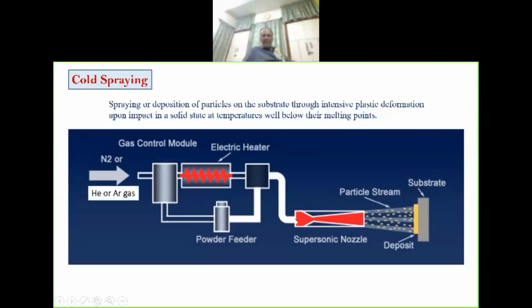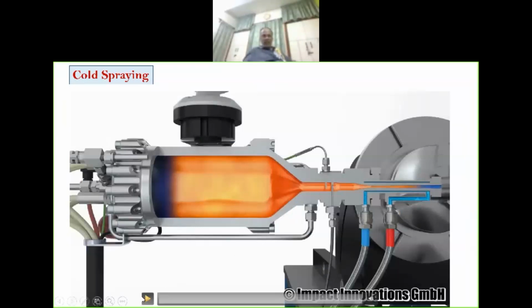pass it to a converging-diverging nozzle at very high speed so that the particle deforms and sticks. No melting, no oxidation, no phase transformation, the layer is compressive. Of course, it's not meant for brittle materials. I have a video, it's similar.